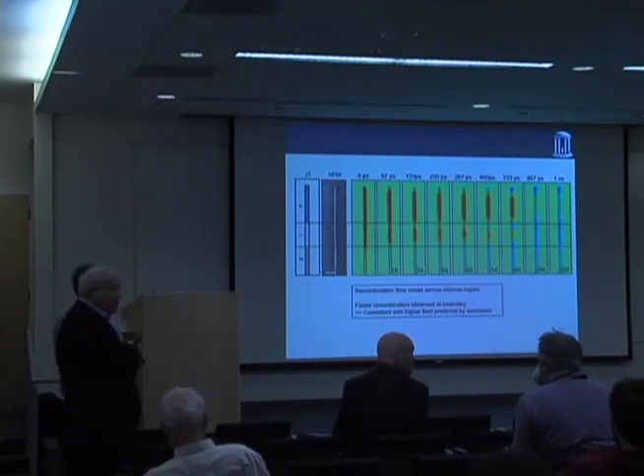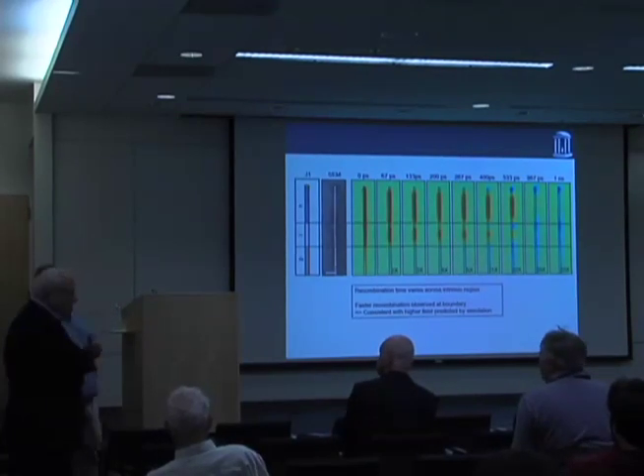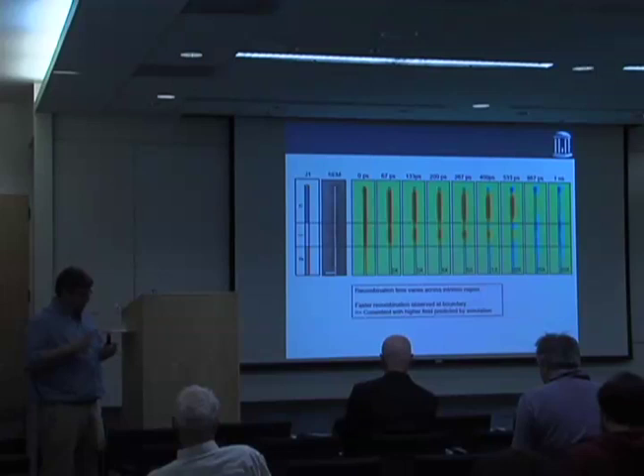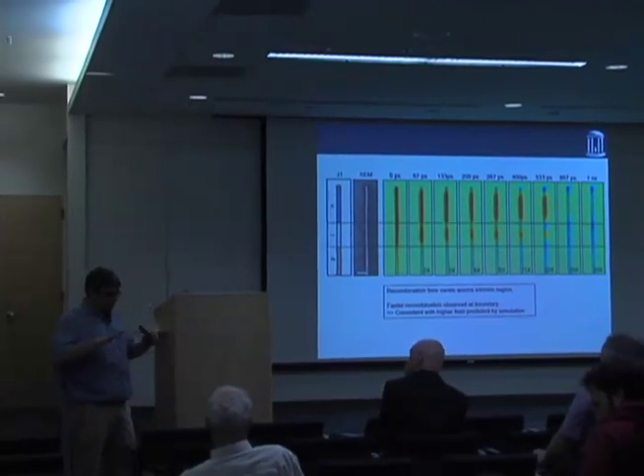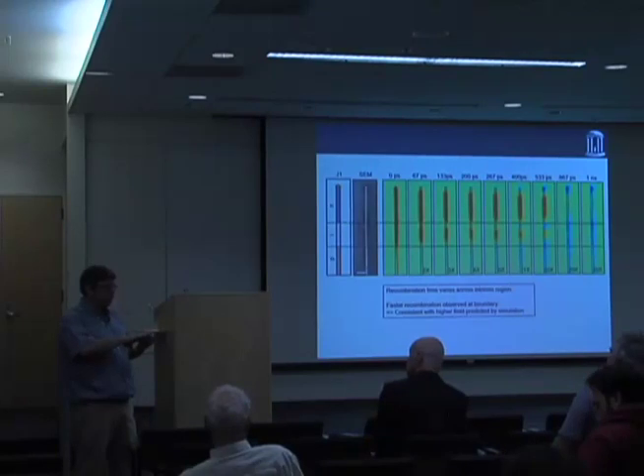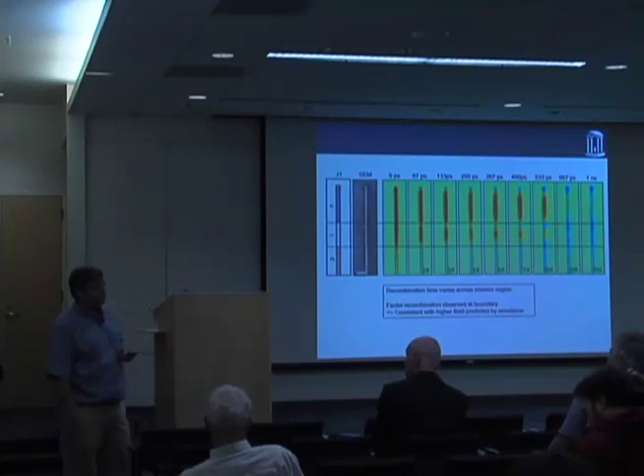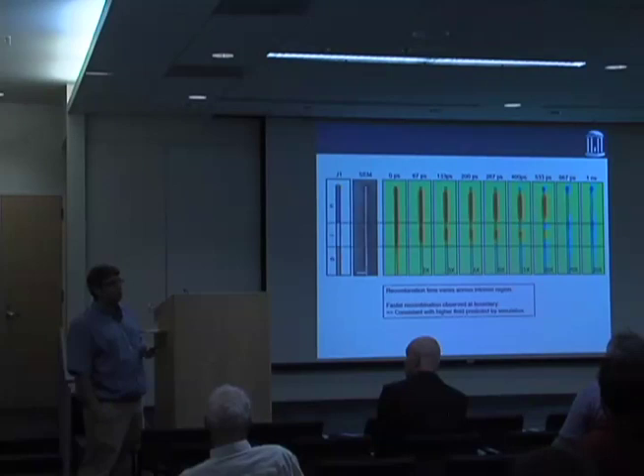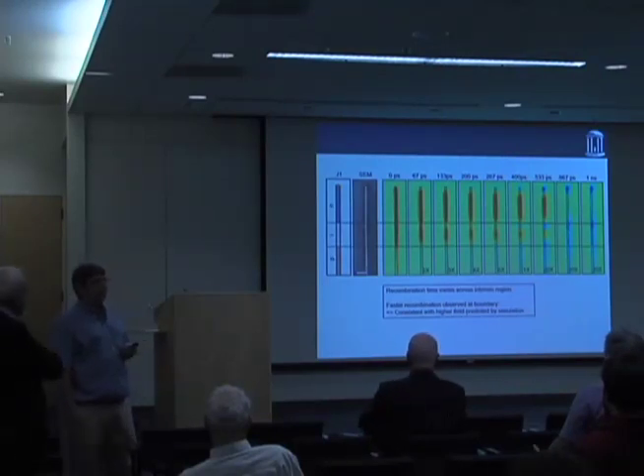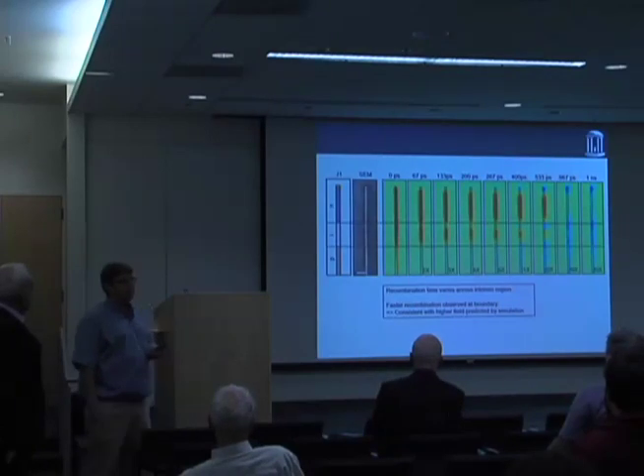Oh man, that would be so cool. So yes, Jim's group, he's my best friend, and he has this ability where he can take one of these mats and collapse all the wires, and then fuse the wires through a process that looks like it spot welds the wires together. We've started looking at those structures, but the carrier recombination in those junctions is really fast, and that becomes a problem, because if the carriers recombine, they don't have time to move anywhere. We're still trying to get samples where the carrier lifetime is long enough that you could actually observe it.